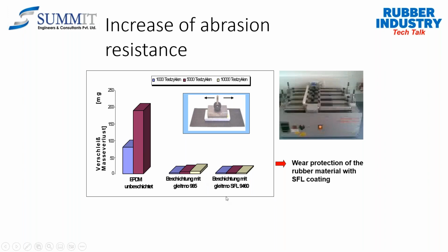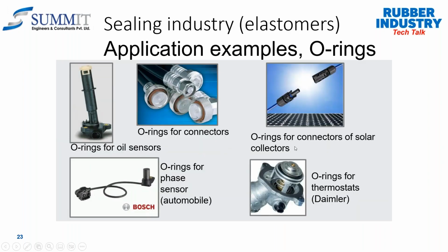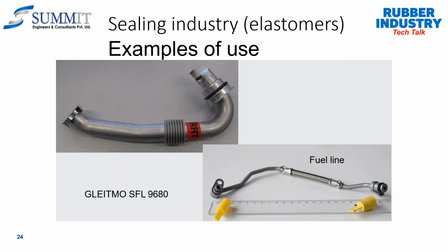In the sealing industries, you'll be able to find the O-rings for the connectors, O-rings for the solar cells, O-rings for the thermostats, O-rings for the phase sensor, especially for the automotive oil sensors. So many other applications where this PTFE coating or the dry film lubricated coatings are being applied. In the sealing industry, you can see the fuel lines where this same material has been used and the life has been extended to a larger extent.